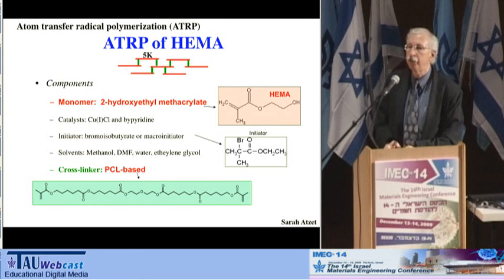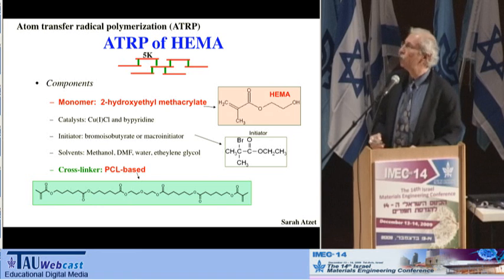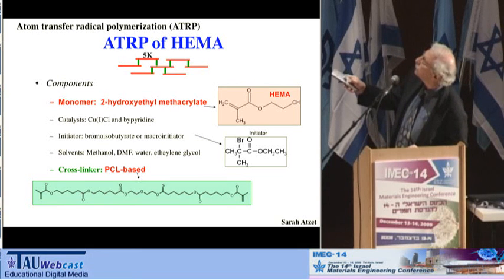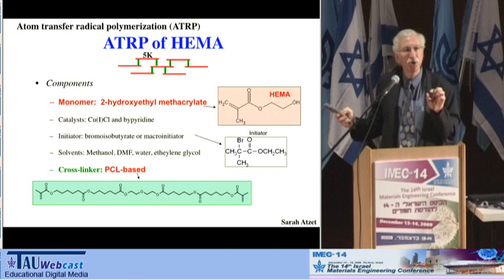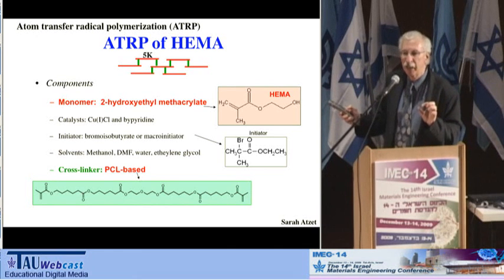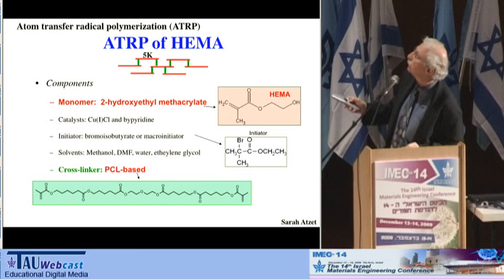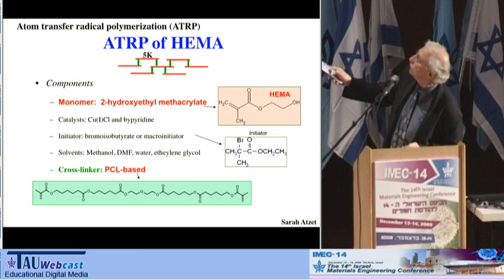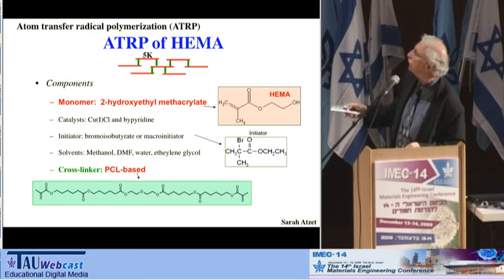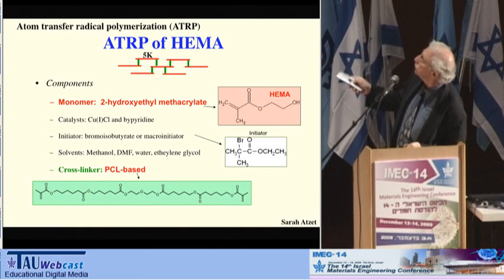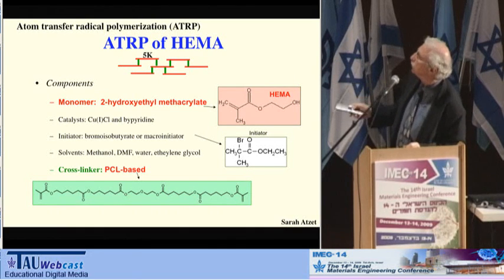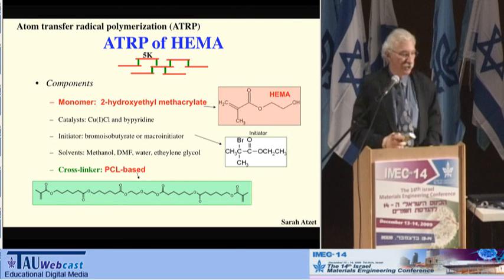So we used a relatively new method in polymerization called atom transfer radical polymerization, ATRP, which gives us very precise control of the molecular weight and molecular weight distribution of units. And so we can put in little 5K segments of HEMA cross-linked by this degradable crosslinker. This talks about the particular initiator we're using, and this is the crosslinker I showed you before.